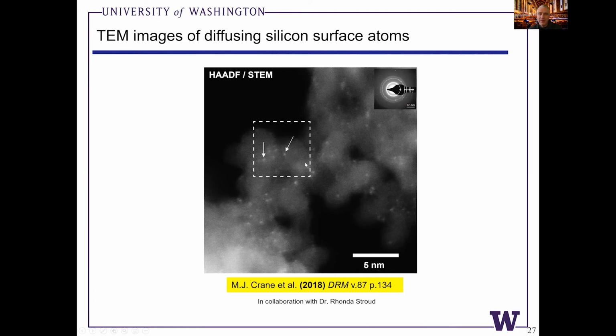And I apologize, I don't have a movie of this, but Rhonda was able to see these silicon atoms moving on the diamond materials. So we think these are just silicon atoms she was able to see from vacuum pump oil in the lab. We think these are silicon grease, effectively silicon atoms that are diffusing on the surface. So we were confident that these atoms were not embedded within the diamonds themselves. They were moving around on the surfaces of the diamond nanocrystals we had made.